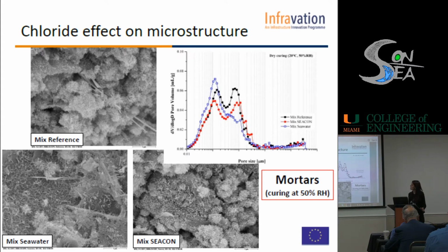The first one is around 0.1 micron and is typical for this type of materials. Instead, the other one is around 1 micron, so bigger pores, and this is completely different from the other case, so water curing, because in this case the development of the hydrated phases is not complete. So the bigger pores are in this case empty, except for mixed seawater. In this case it doesn't have the bigger pores due to the salts that precipitate in them, closing them.